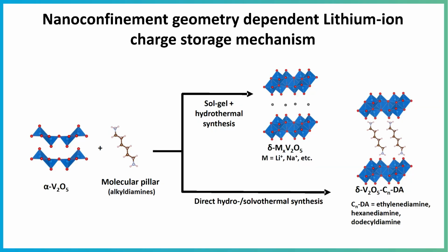spacing. So in our work, we investigated how changing this interlayer spacing affects the performance of the lithium-ion storage. To be specific, we worked with vanadium pentoxide, and we used this approach of pillaring. We used this pillaring approach to manipulate the interlayer spacing of our vanadium pentoxide.